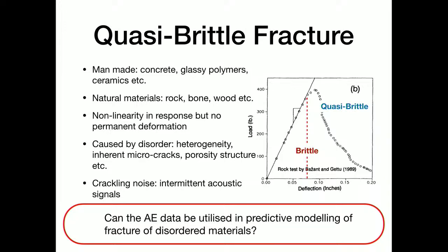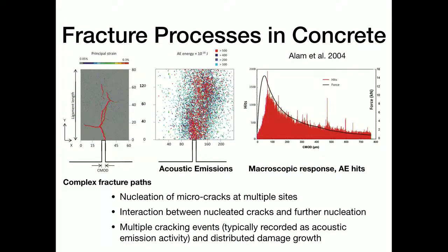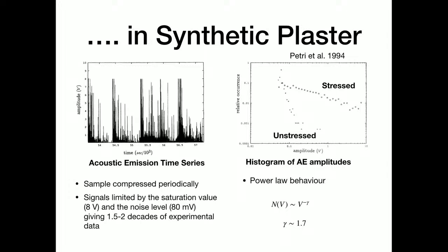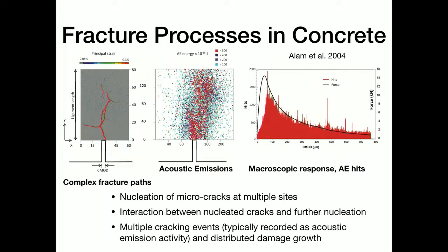Now AE signals have been utilized in several contexts in engineering applications. So here what I'm showing is a concrete beam which is notched, and if you see visually, these are the eventual crack paths that form, fairly complex but localized. But if you look at the acoustic picture of that, you see that the damage events are occurring over a much larger span, and there is a huge process zone that is involved in making these much sharper localized cracks.